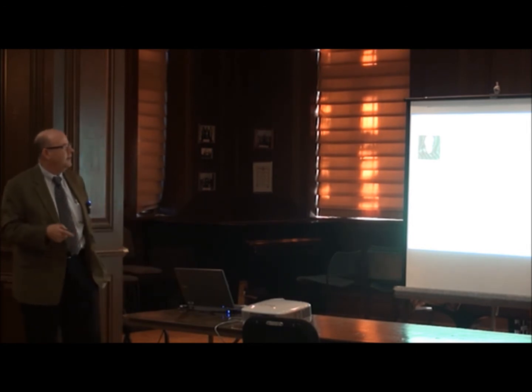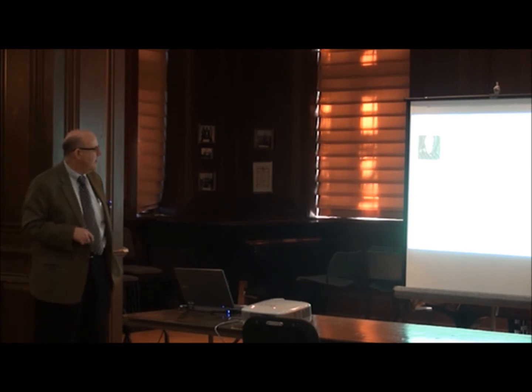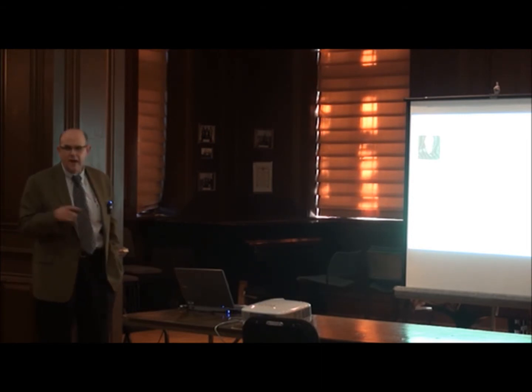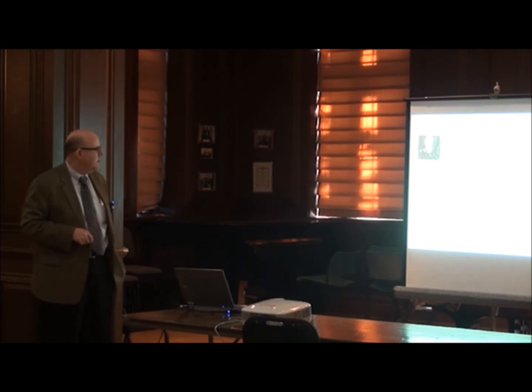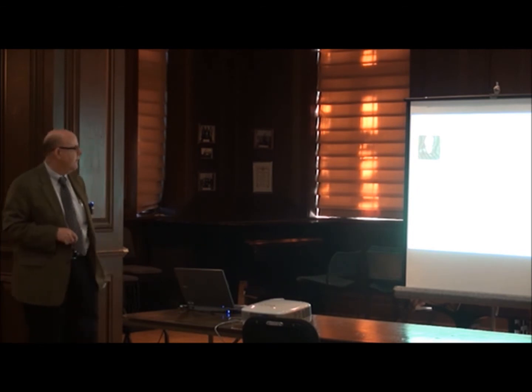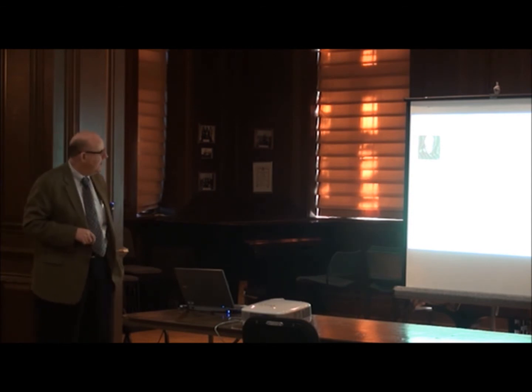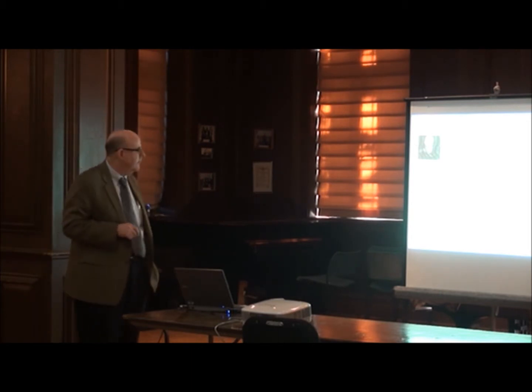And from that, he could derive that there was indeed a force that was supporting the load. The interesting thing to recognize is that the frictional force in these simple little taper bearing things depends on some geometrical factors. It depends on the viscosity: the higher the viscosity, the higher the friction. It depends on the speed, higher the friction, and the area of interaction, the length. The interesting thing, though, is it depends inversely on H2, that little gap there. So the narrower the gap, the higher the friction. We want to keep that in mind, okay?